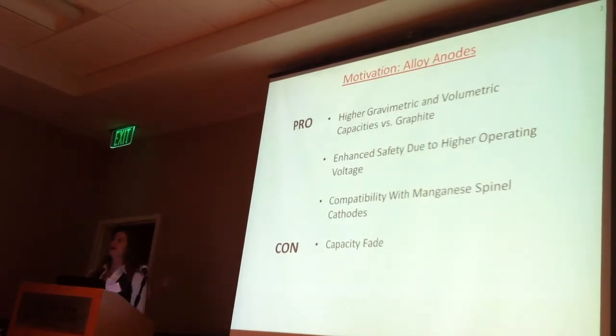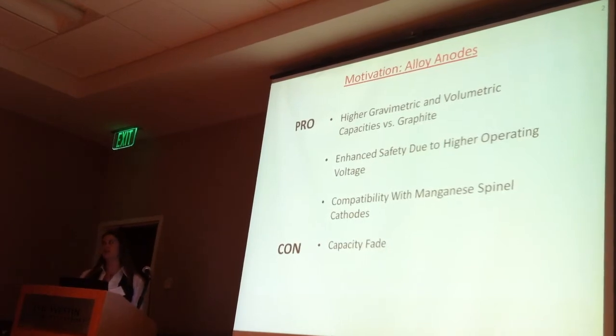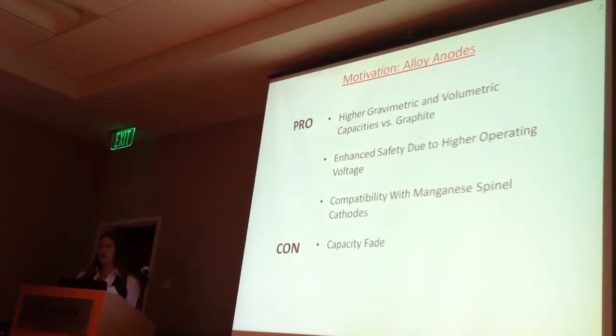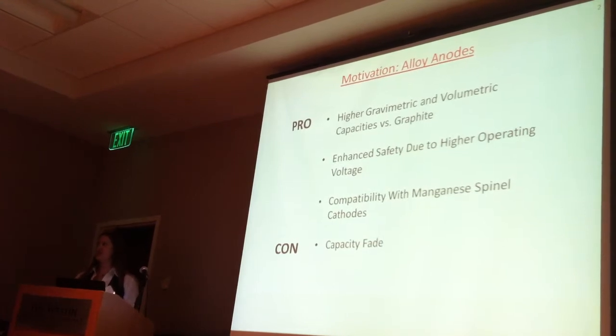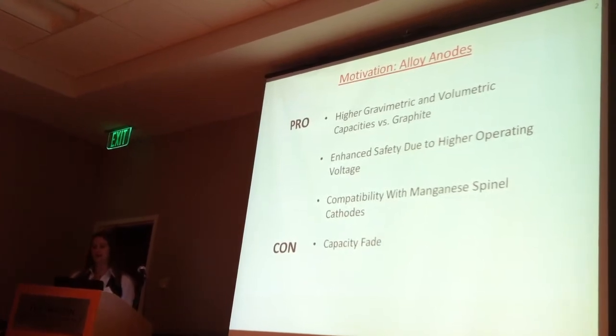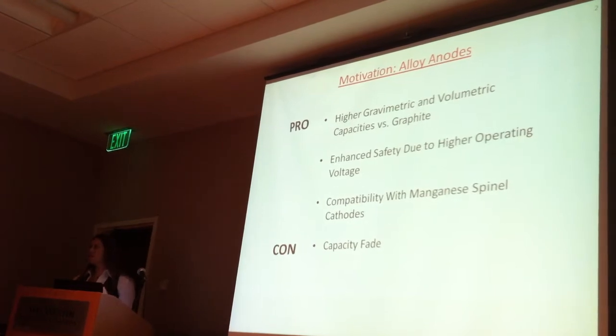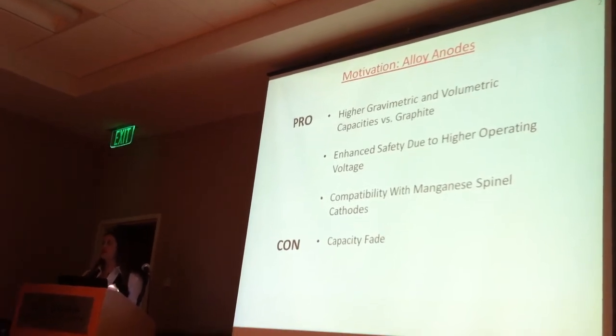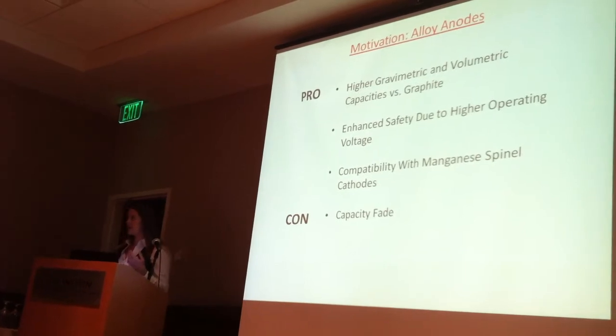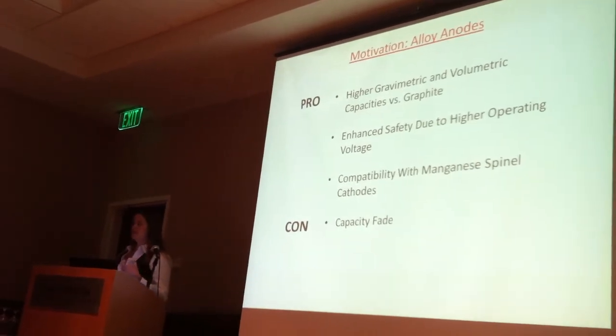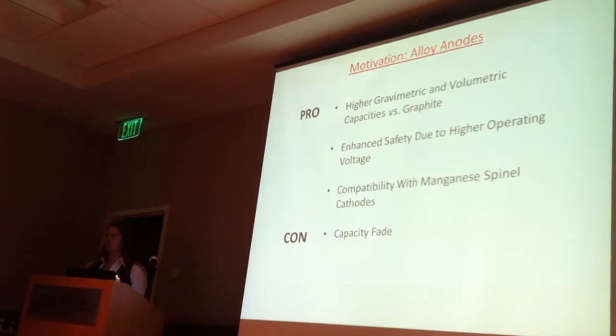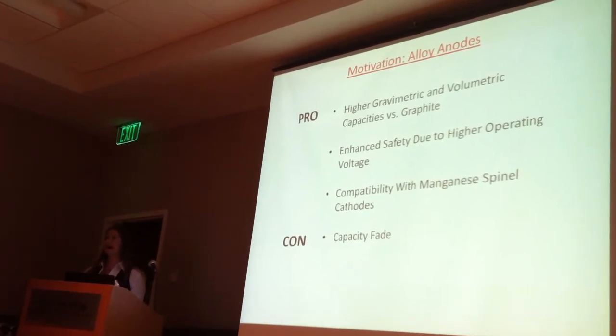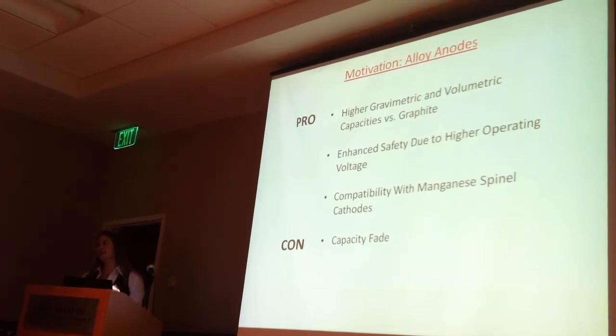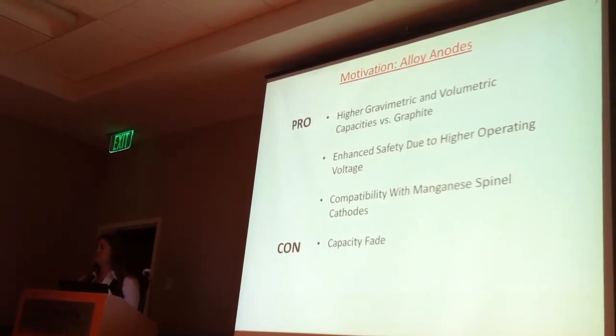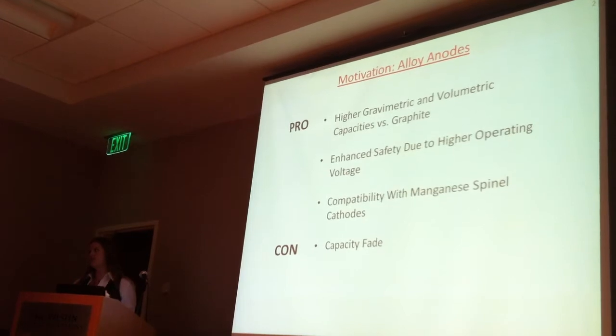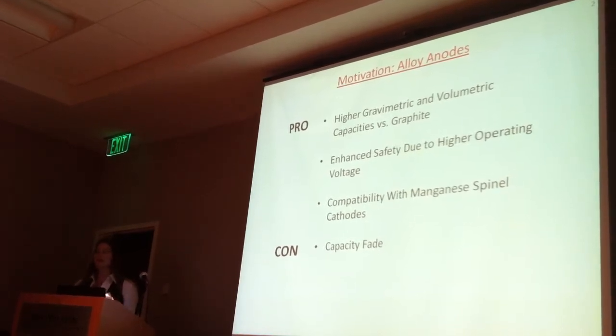So the reason we want to study alloy anode materials is we're looking for an alternative to graphite. With a lot of alloy anodes, you can get a higher volumetric and gravimetric capacity compared to commercial graphite. Also, the potential at which these alloy anodes react with lithium is far above the potential at which lithium plating occurs, which makes them safer. Also, we're looking for some anode materials that are compatible with manganese spinel, something that doesn't suffer from the manganese poisoning that we see with graphite. And alloy anodes offer a lot of options in these categories.